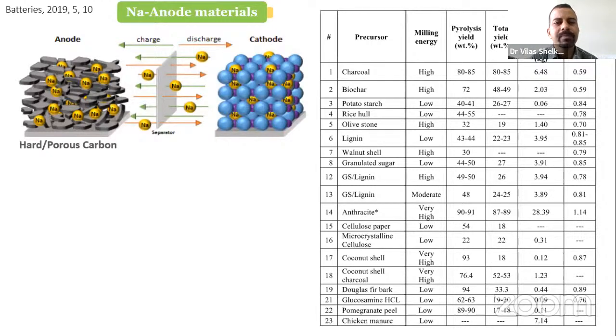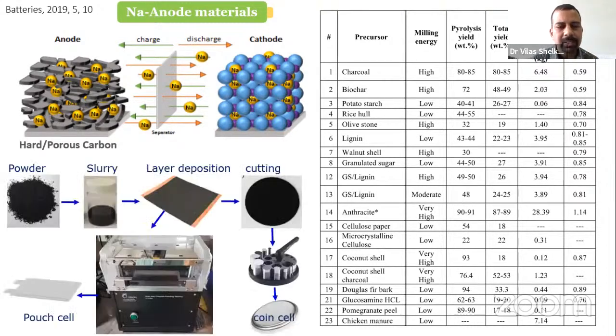So now you have an anode material, and you have already selected your cathode material. So then it is time to combine these anode and cathode materials to make a battery. The process of making a rechargeable battery is quite simple. It is being used for all types of battery, even lithium-ion battery or sodium-ion battery. So you essentially need a powder of carbon, powder of cathode material, and powder of anode material. Then by using a binder, you make a slurry of this powder separately, and then you make a layer on a certain kind of electrode or current collector. You can use copper or you can use aluminum. Aluminum, as I said, is a preferred choice for sodium-ion batteries.